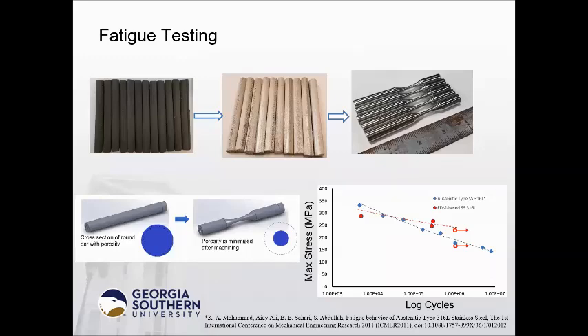And for fatigue testing, I printed some round bars and put the round bars in the furnace for debinding and sintering. Then I use a CNC machine to machine the round bar. You can see it has a smooth surface roughness compared to the as-built surface. So the fatigue bar is tested using the MTS fatigue tester. The thing is that you can see after the CNC machining, some porosity underneath the subsurface of the round bar is removed, so it has less porosity inclusion in comparison with the as-built surface. So here, the porosity is minimized after machining in the gauge section of the fatigue bar.